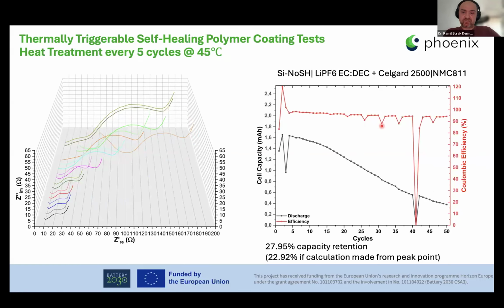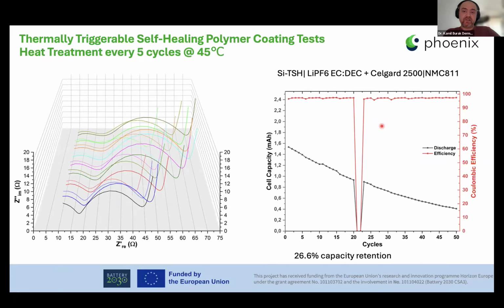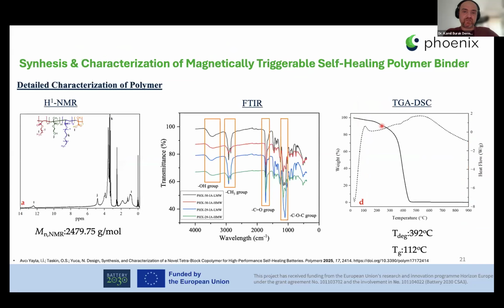After that, these were the results for the silicon without self-healing. When we applied the self-healing polymer coatings on the tests, the capacity retention is still quite similar to the ones without self-healing. So the results basically don't go to meaningful levels.